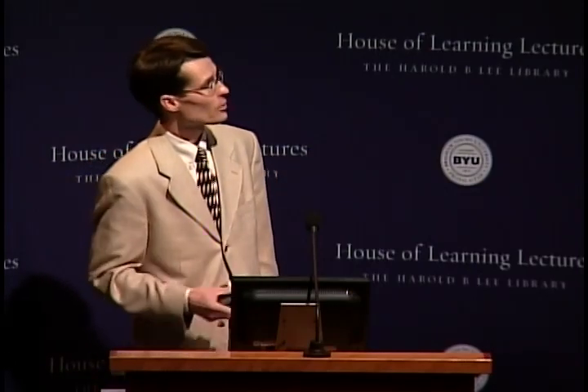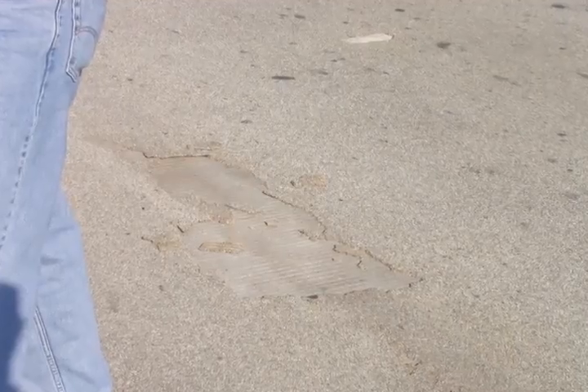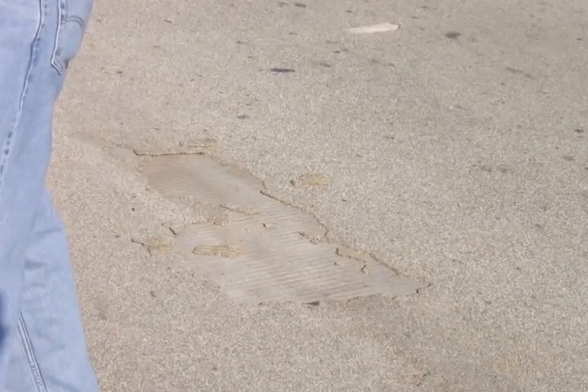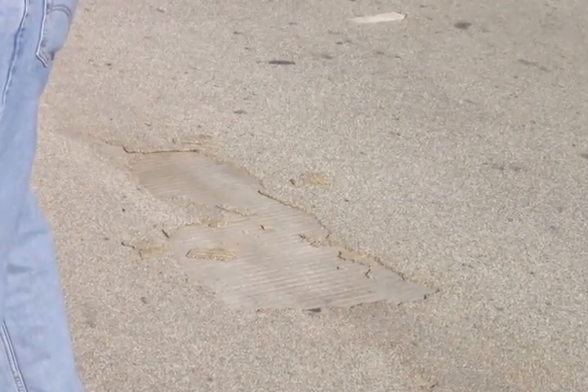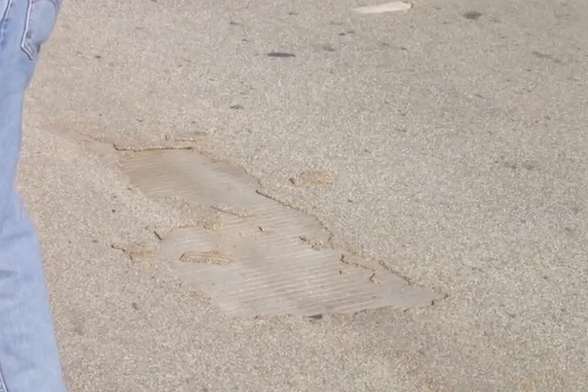The third and final type of protection I'd like to share with you is the use of surface treatments on bridge decks. You're looking in the center at the original concrete surface. What's been placed on it is an epoxy product, which is placed in a liquid form, and then afterwards, aggregates or small rocks are broadcast into the epoxy to produce a very highly skid-resistant surface that, when placed properly, will provide protection against chlorides and water. That is, it will be impermeable to the ingress of water or chlorides. In this case, no doubt the surface was not prepared properly, and debonding of that layer occurred.